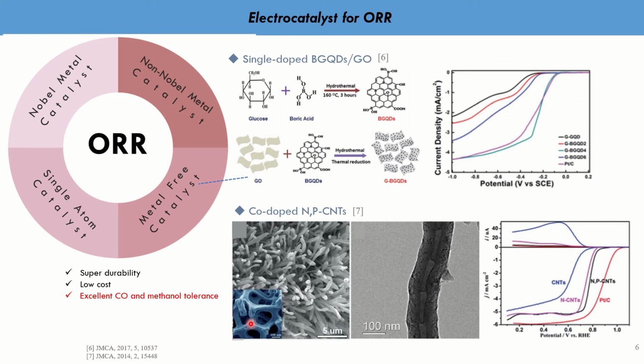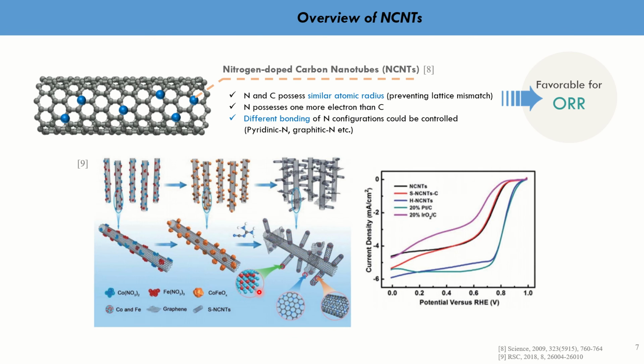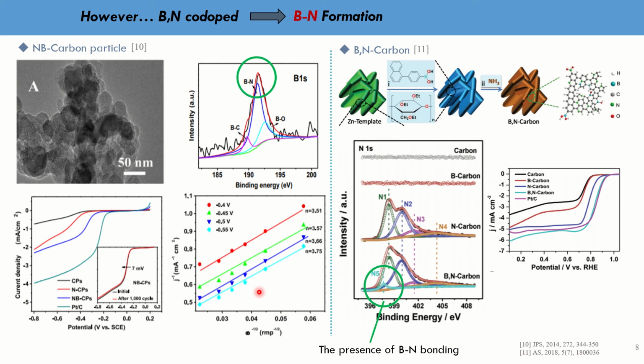Besides single heteroatom doped materials, multiple heteroatom co-doped carbon materials exhibit impressive ORR performance due to the synergetic coupling effect between different heteroatoms that could facilitate the electrocatalytic reaction of oxygen. On the other hand, it has been reported that nitrogen-doped carbon nanotubes exhibit strong electrocatalytic activity for ORR and enhance the adsorption of oxygen molecules on the active center, therefore weakening the oxygen bonding and lowering the ORR barrier. So we want to design a boron and nitrogen co-doped carbon ORR electrocatalyst.